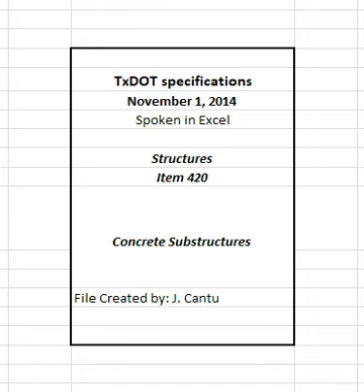Use the Concrete Works copyright software available from the department, or another approved method based on the guidelines in ACI 207, Mass Concrete, to develop the heat control plan. The department will make available technical assistance on the use of Concrete Works copyright. Develop the heat control plan using historical temperature ranges for the anticipated time of the mass placement. Recreate the plan if the work schedule shifts by more than 1 month.